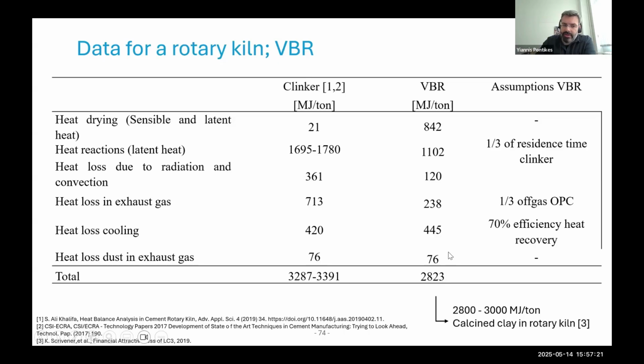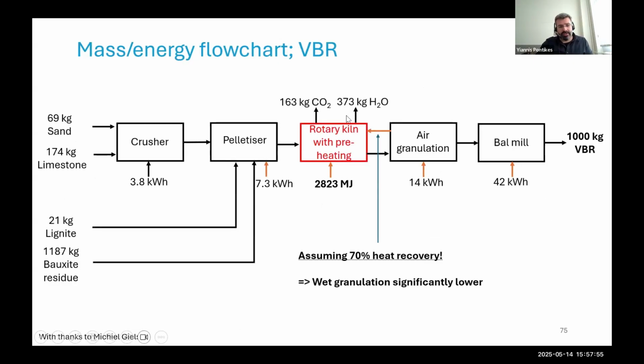You can improve that. Here we have things that we have not actually been optimizing, but let's keep it simple now. The first thing is that your energy requirement is fine for making this happen. Second thing, interestingly, is that you will not be using, ideally, carbonates. If you want, let's say, calcite, you can take it from BOF slag, or from other things that are already decarbonized. So you don't need the energy requirement for the dissociation of the limestone. That's also important. Where would you see that in the whole process? It's mostly here. The other steps are not so energy demanding.